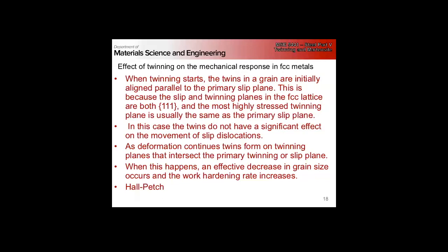What's that? We're disrupting slip planes. Yeah, so you hit the 2 parts, right? We're impeding orientations, or we're impeding dislocations. So basically, every time you put in a twin, you're reducing your grain size. We've got the Hall-Petch effect going on. Then we're changing orientation, so we're adding new grains. So we have an additional hardening effect that comes from texture,